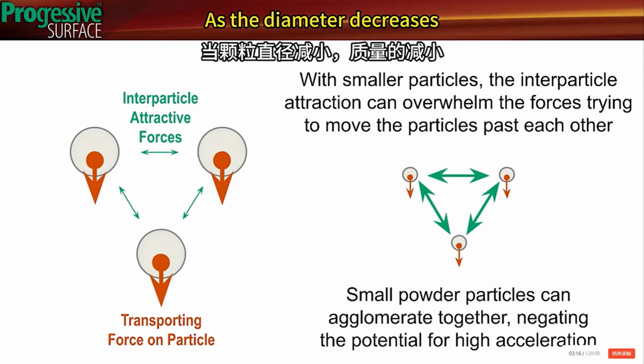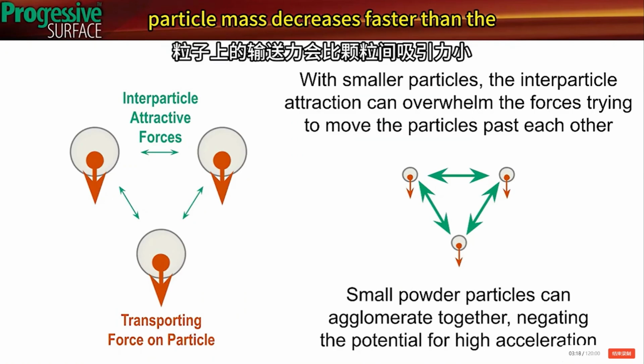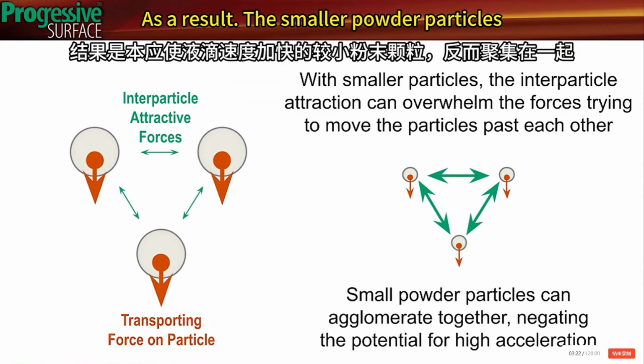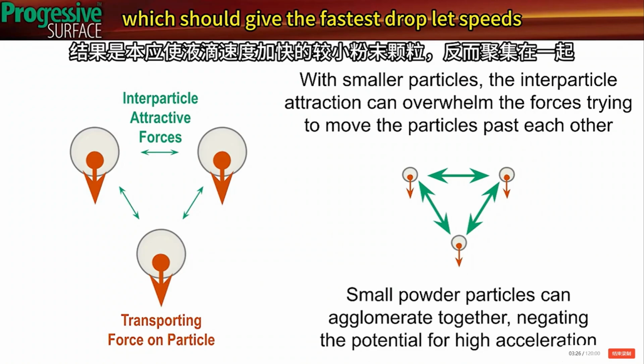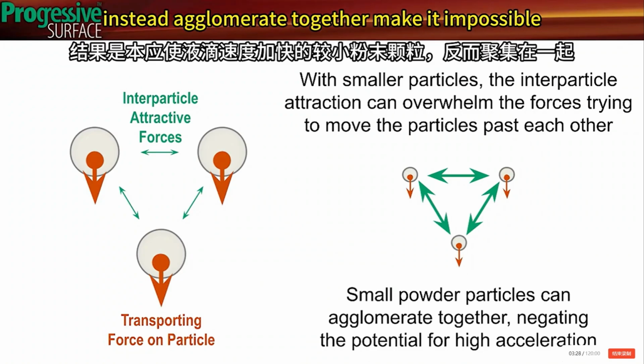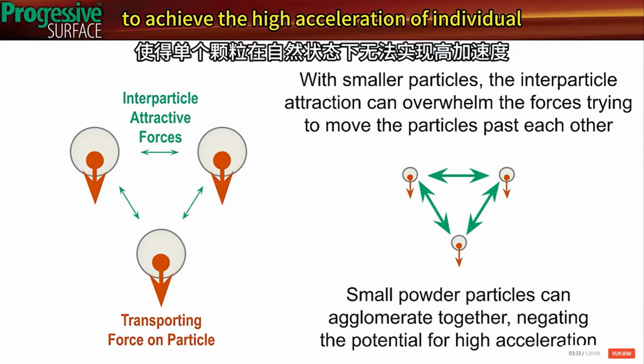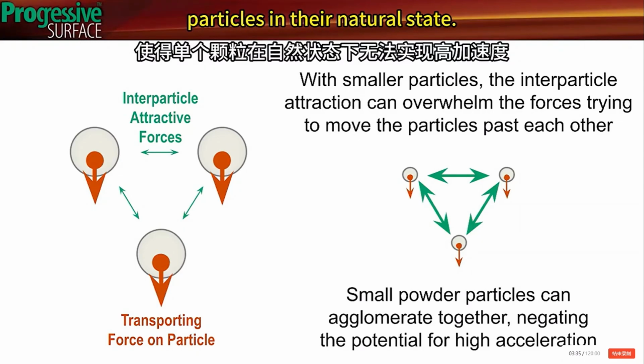As the diameter decreases, particle mass decreases faster than the attractive potential between the particles. As a result, the smaller powder particles, which should give the fastest droplet speeds, instead agglomerate together, making it impossible to achieve the high acceleration of individual particles in their natural state.